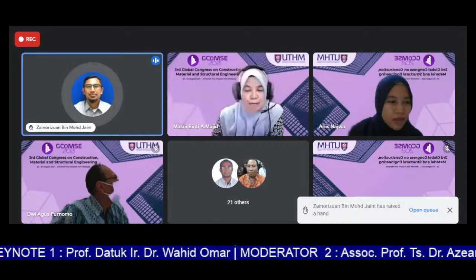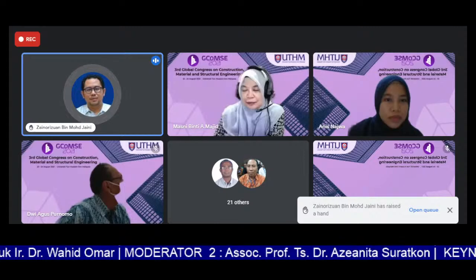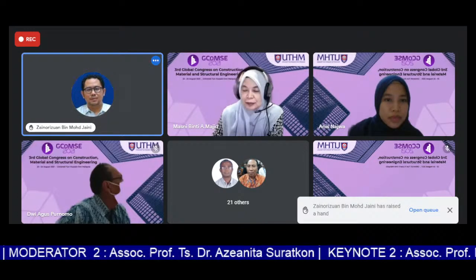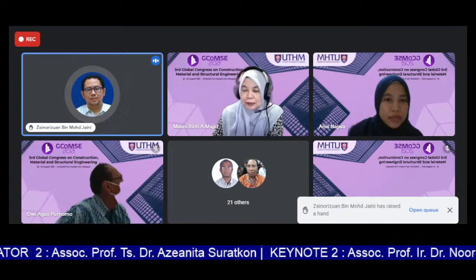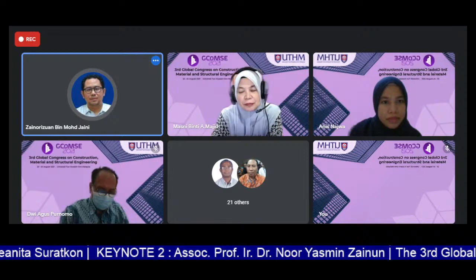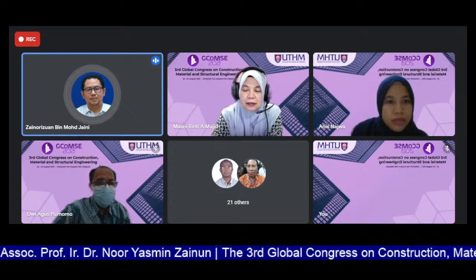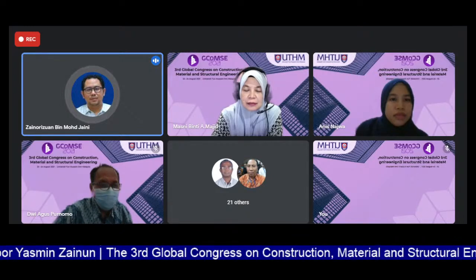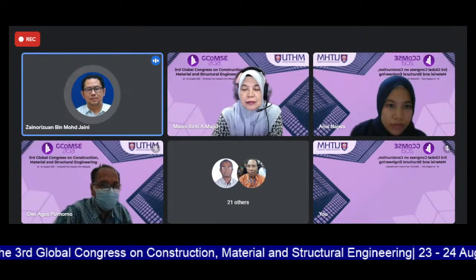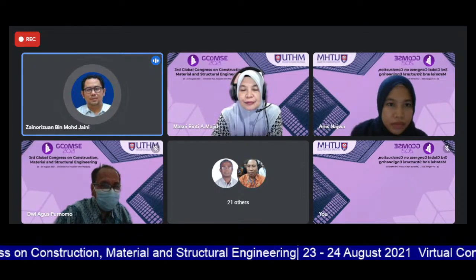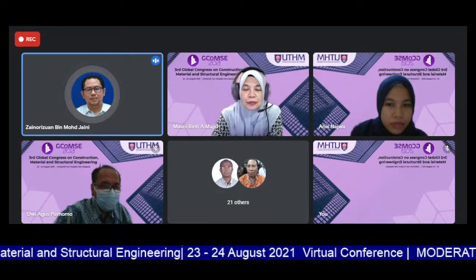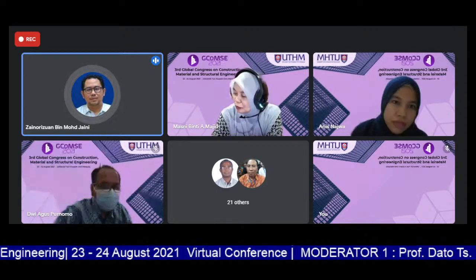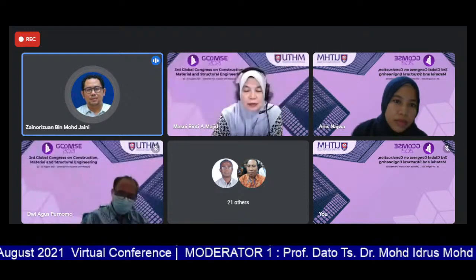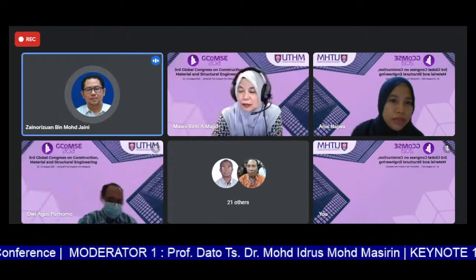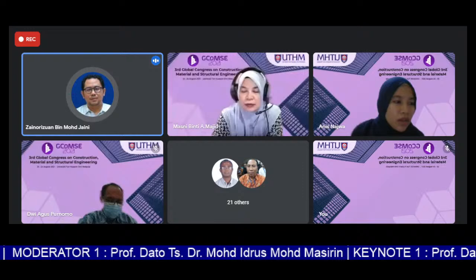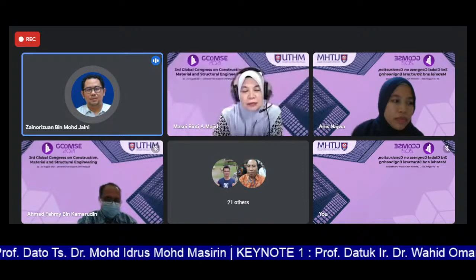Okay, Assalamualaikum. To the presenter, I have one question regarding your finite element modeling. Because you are using rubber crumb, which degrades in the long term, the elastic properties or other mechanical properties may be slightly degraded or reduced from the initial condition. So in your finite element model, how do you consider the degradation of the material properties in your material model? You are using Drucker-Prager, right? So how is this degradation of the material properties considered in the finite element? This is my question.